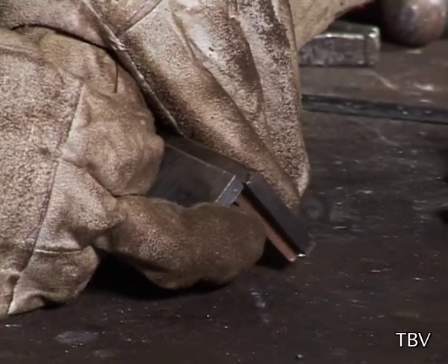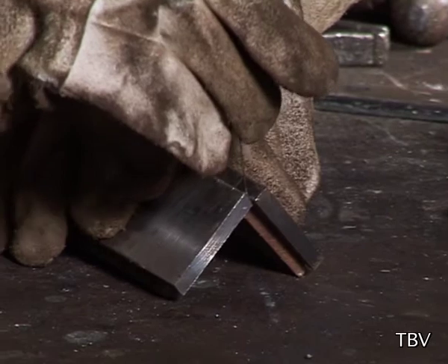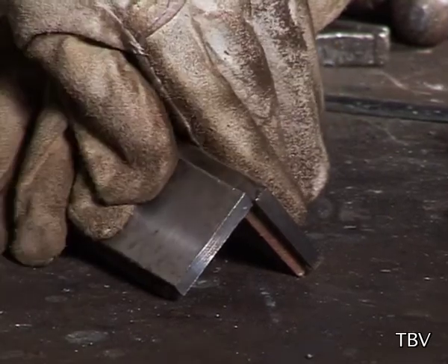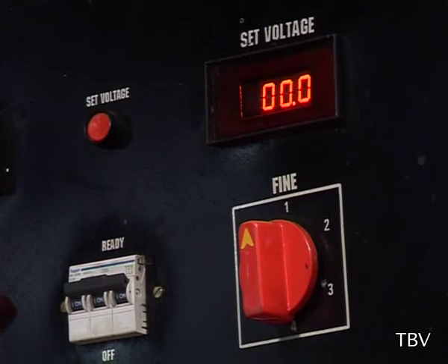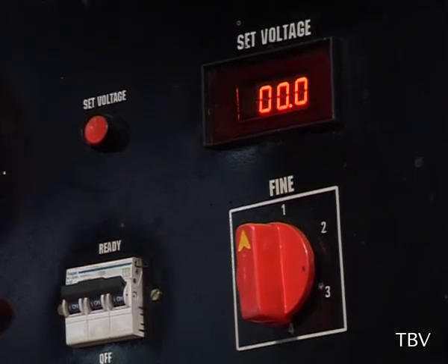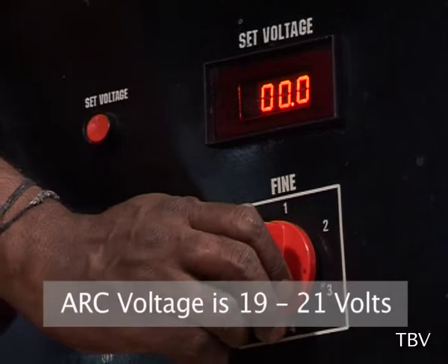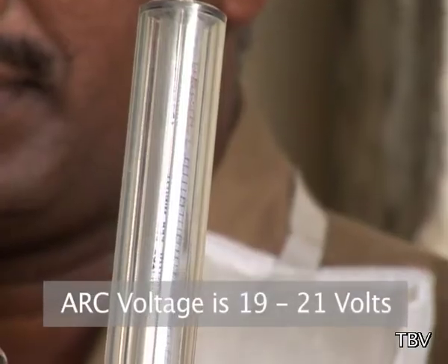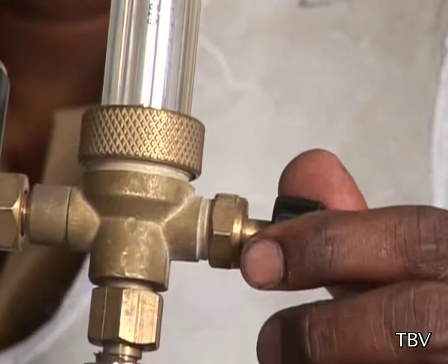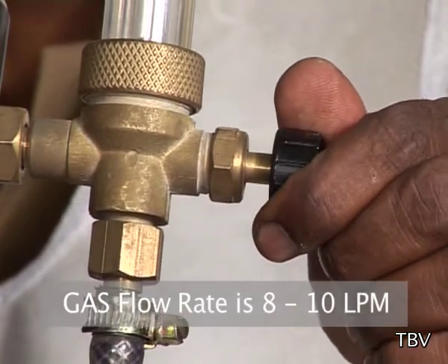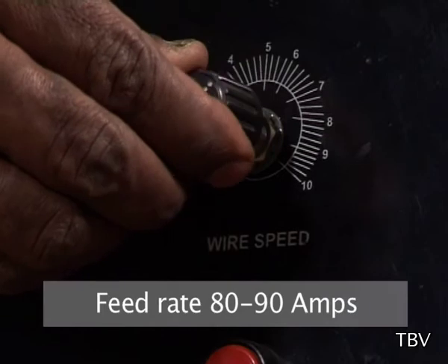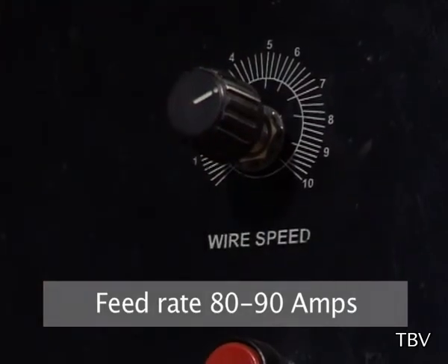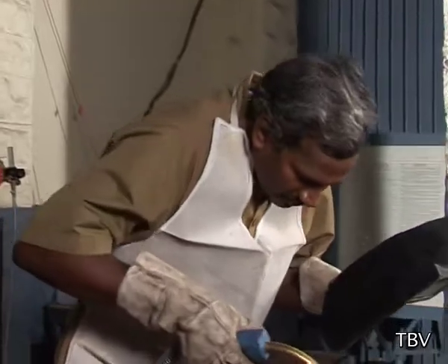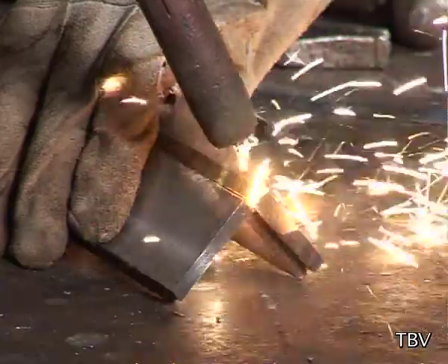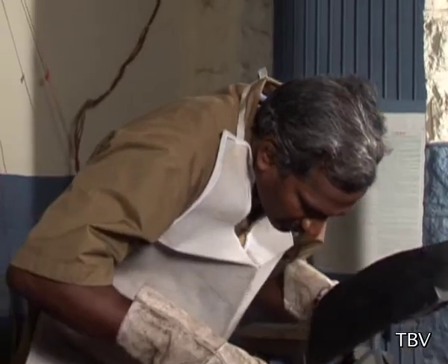The welding machine is on. The CO2 gas heater is switched on 5 to 10 minutes before starting the welding to form CO2 gas as it is a liquid gas. With an arc voltage of 19 to 21 volts for dip transfer mode, the flow meter is fixed as 8 to 10 LPM. Set the feed rate. The same 0.8 mm diameter wire spool is used for welding. Tack weld on both the ends.